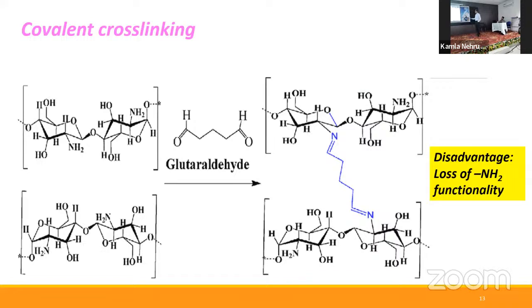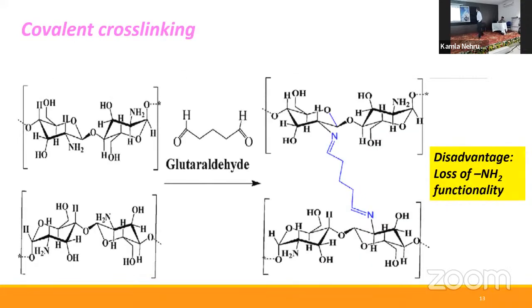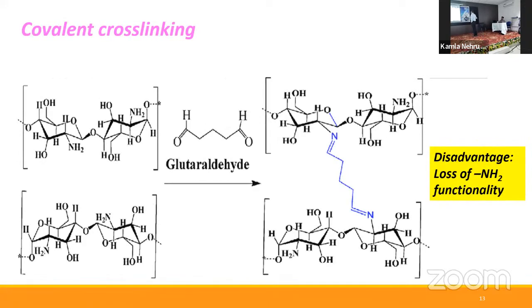There is a possibility of covalent cross-linking. The basic chemistry knowledge tells me that the NH2 group can be combined with the aldehyde group, and if I use an aldehyde like glutaraldehyde, or say any dialdehyde other than glutaraldehyde, it can act as a bridge between the NH2 groups of the two chitosan moieties, and we can carry out the cross-linking of chitosan by using such type of glutaraldehyde. But the problem of this is that the NH2 functionality which was present over here is lost because of the cross-linking phenomena.